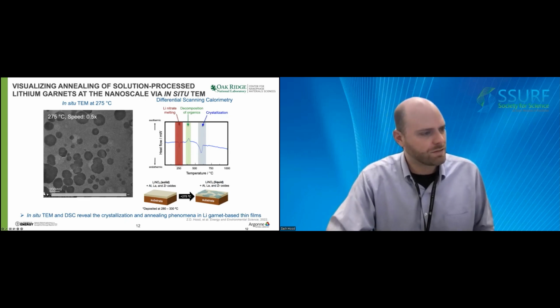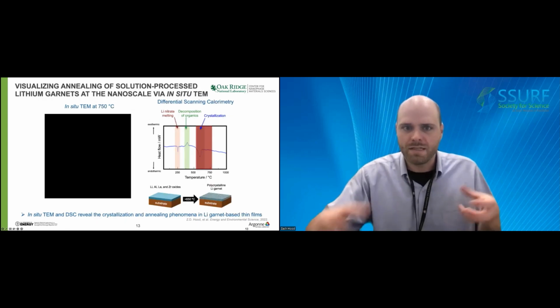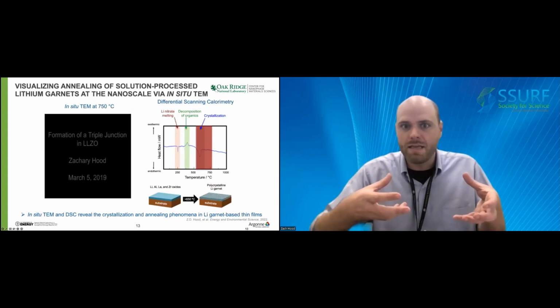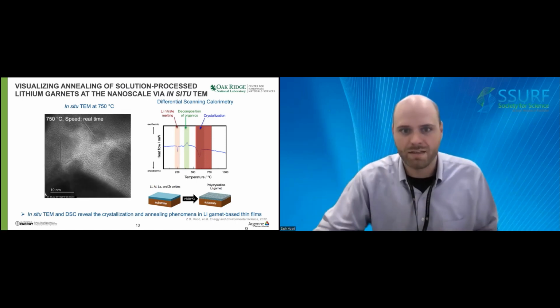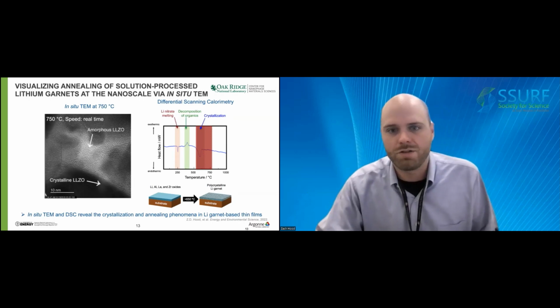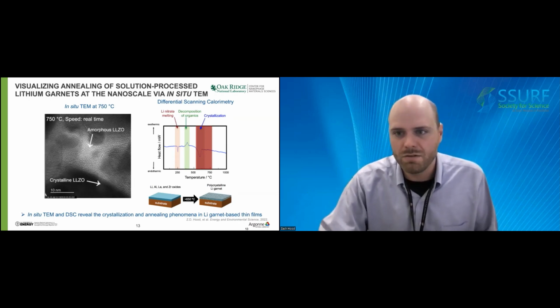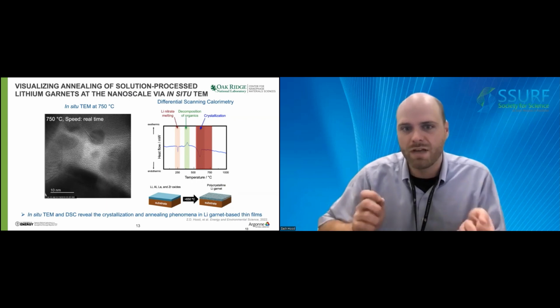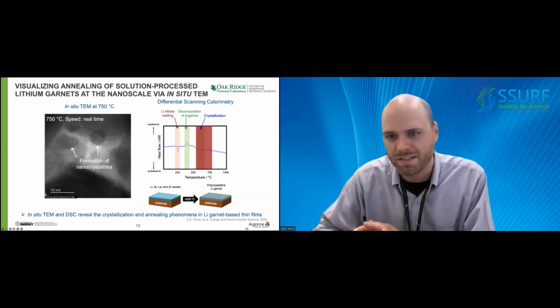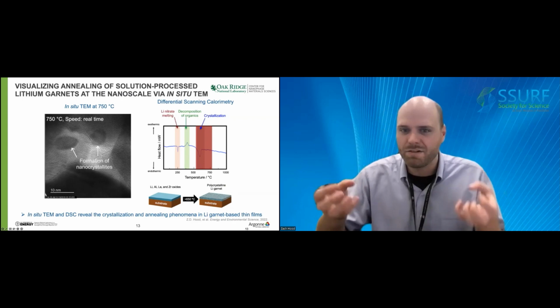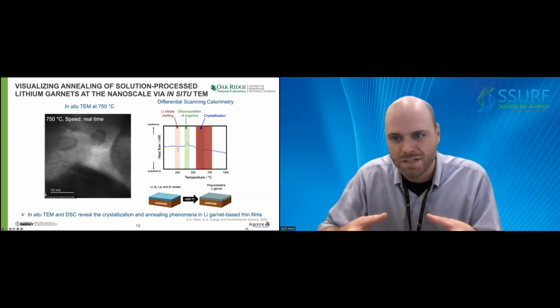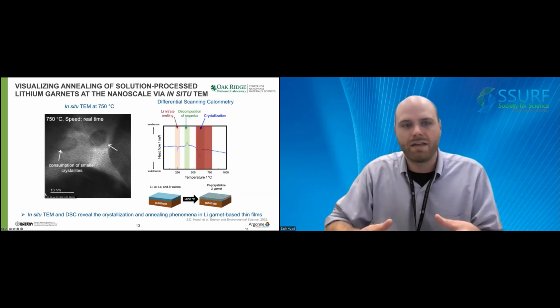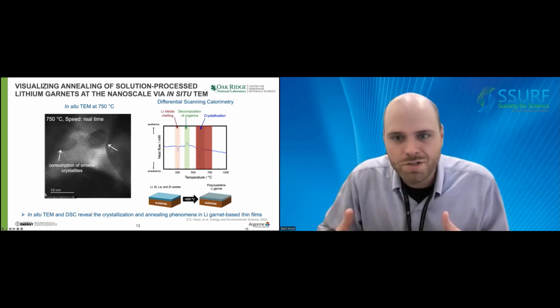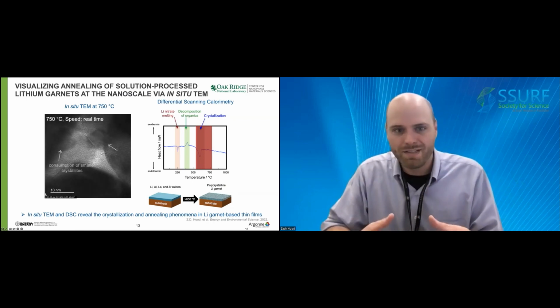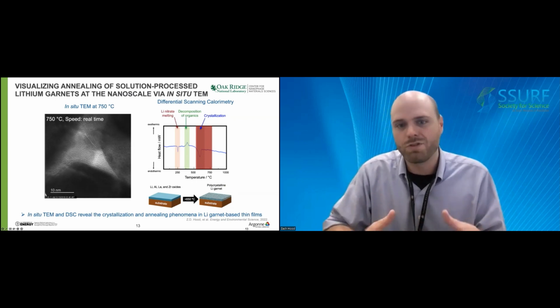But importantly, with the crystallization of these materials, we can take our films to the temperature where we would want to crystallize our material to get a dense solid-state electrolyte. And we can observe the nanoscale transformation of these films. So as you can see in this video, the film has amorphous grain boundaries and larger crystalline grains. And as the material is heated, we can see these nanocrystallites start forming at these grain boundaries, which then get consumed by the larger grains. So then the larger grains continue to grow inward, and eventually they form a triple junction.